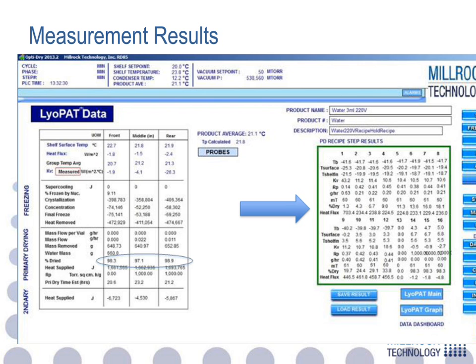Now, the interesting part of this screen is if you look at the right-hand side where that arrow is pointing, if you're running a recipe, at the end of each step of the recipe, we will take a snapshot of the product temperature, surface temperature, shelf temperature, KV, cake resistance, mass flow, pressure, percent dry, and the heat flux at each step. And this is really a neat tool for those of you that are interested in doing something like a design space. Because what you can do in a recipe is you could say, all right, I want to run my shelf temperature at -5, and I want to see what happens when I change the vacuum level. I want to see what happens to KV and my mass flow.